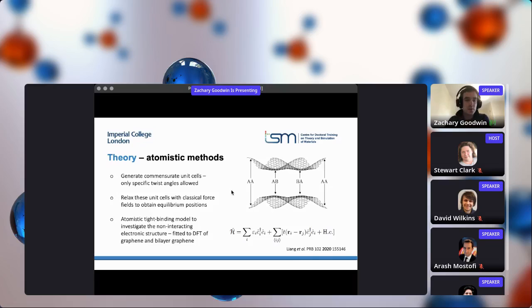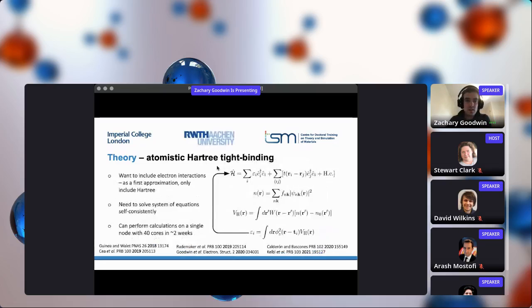And then using these atomic positions, we have an atomistic tight binding model to investigate the non-interacting electronic structure of this material. The hopping parameters for this model are basically fitted to DFT electronic band structures of graphene and bilayer graphene. Right, so then we want to look at the interacting properties of this material.